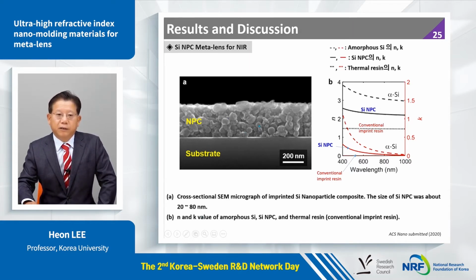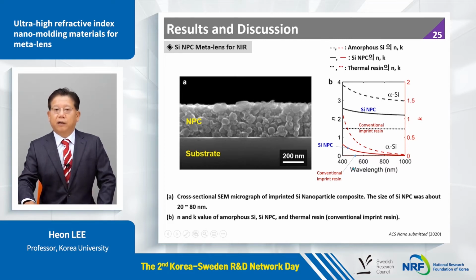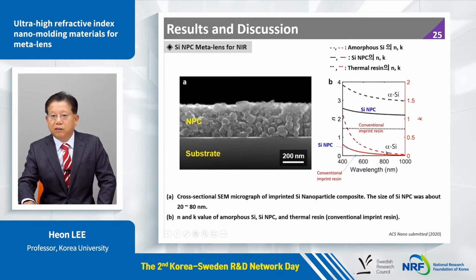And you can clearly see some nanoparticles, and the nanoparticles are well connected with the polymer resin. Its refractive index is somewhere between the bulk silicon value and the conventional imprinted resin value. This one is in the middle between the amorphous silicon bulk material and the imprinted resin. And this is the silicon's extinction coefficient and the imprinted resin's extinction coefficient. My imprinted resin has some middle value.